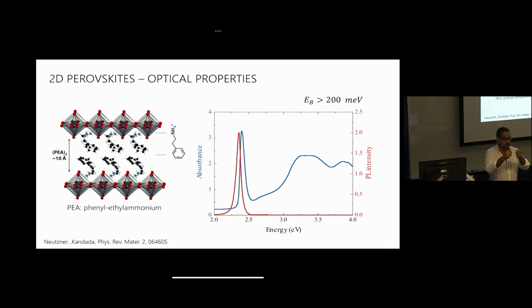The energy that it takes to separate electron and hole into free carriers is 200, 250 millielectron volts. That's a high binding energy. That's about 10 times kT at room temperature. So it's a very strongly excitonic system, and you've got this very well-defined resonance. You've got this photoluminescence spectrum, which reflects that as well. And the whole context of my talk is going to be on what the nature of these excitonic states are.